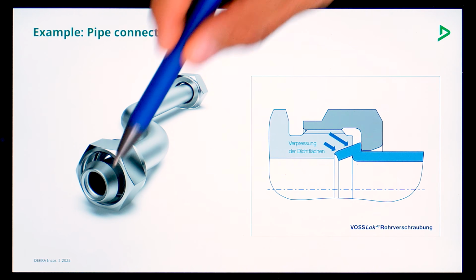Yeah. And if you have only metal on metal, you only flatten the very small roughness of the surface, and if you have a high pressure, you can flatten these small roughnesses, and therefore you get really good surfaces, so that you have a high tightness in these connections. Okay, but then you need to work really hard at making these surfaces really smooth. So both parts should be really smooth. Really smooth. Okay, cool.